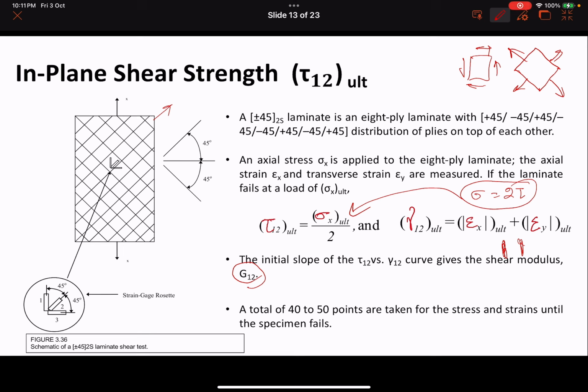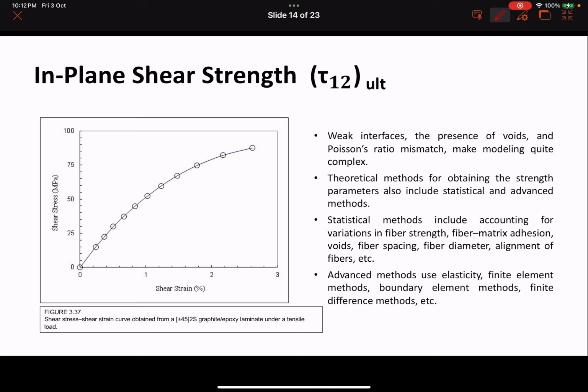Here I think the shear modulus for graphite epoxy lamina is 5.566 gigapascals, a low value of course. Tau 12 ultimate is 87.57 megapascals. That's not too bad in comparison with the transverse values. And the ultimate shear strain, failure strain, is actually good, 2.619%. It's even higher than the tensile strain, meaning if you have plus or minus 45 degree plies, it can stretch further than your normal 0 degree plies. Again, it's the same process, stress versus strain.